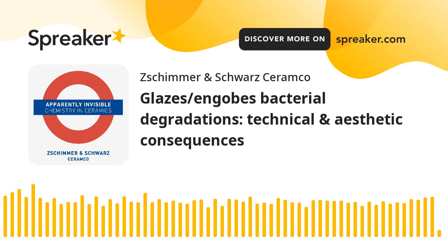And indeed, all the tools used in the departments, such as mills, tanks, pipes, are often contaminated, but we usually notice the degradation only when it has reached a high level of proliferation. In other words, we usually smell bad odors only when the problem is underway. And at that point, the system is entirely contaminated, and if you do not take immediate action, you keep on feeding bacteria by using the organic products involved in the grinding process. So, once the problem has been detected, the sanitization of the entire department is the only way to solve it.